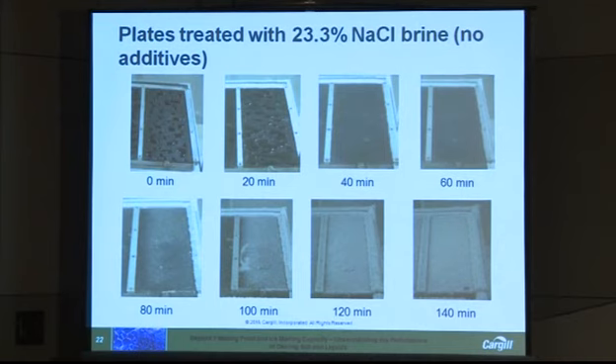So at first, all that happens is we start getting an accumulation of ice melt on the plate. Then as time goes by and it continues to be exposed to more freezing precipitation, that melt layer gets diluted and it builds up, and at some point it begins to freeze at about 40 minutes here. It starts forming this translucent glaze ice layer. Now, is that the failure point for my de-icer? I don't know that it is.